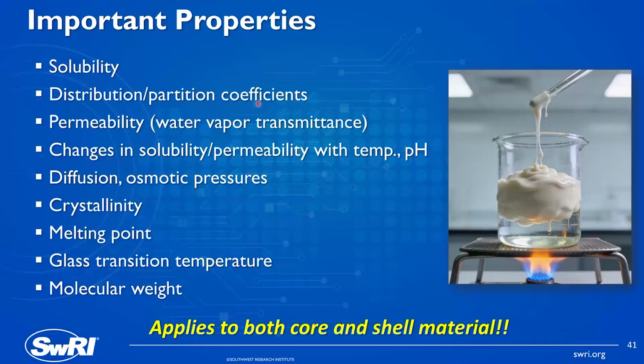And the temperature and pH might also impact permeability of your materials, diffusion, and so forth. Solid materials, are they crystalline? Are they amorphous? Waxes, for example, might need a time afterwards to fully crystallize. If you are working with waxes and fats, what's their melting point, their glass transition temperature? And once you start to think about polymers, molecular weights. Often it's the highest molecular weight that gives you the best performance, but is the most difficult to work with. Whether you're melting it, it's highly viscous, or dissolving it, and you just can't dissolve a lot because it becomes too viscous. So properties to think about as you move forward.